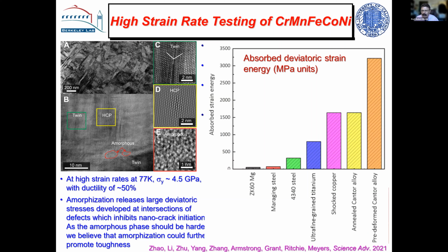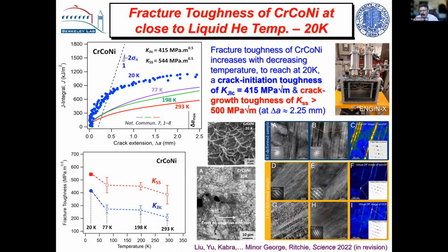Now, the most recent stuff we've done is we went and did liquid helium tests. We went to the Engine-X facility just outside Oxford and did the tests in liquid helium. We have to have big samples, so we're not getting 4 degrees Kelvin. We're closer to 20 degrees Kelvin, but it's pretty cold. And here is that 3-component chrome cobalt nickel alloy on an R curve, J versus crack extension. There's the original data I showed you for room temperature, dry ice, and liquid nitrogen temperature. And this is the one at the liquid helium temperatures. And we are measuring toughnesses here of 415 megapascal root meters. And we're measuring the crack growth toughnesses, which I call the steady state toughness up here, of 500 megapascal root meters. And to my knowledge, that is the highest toughness ever measured in a material.